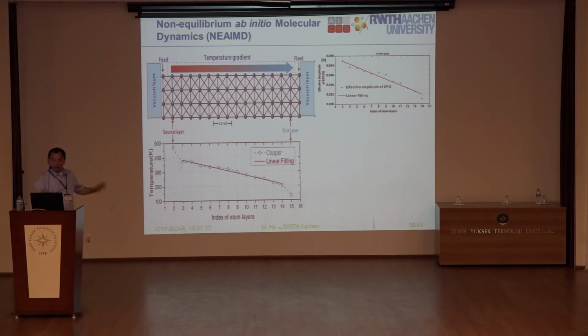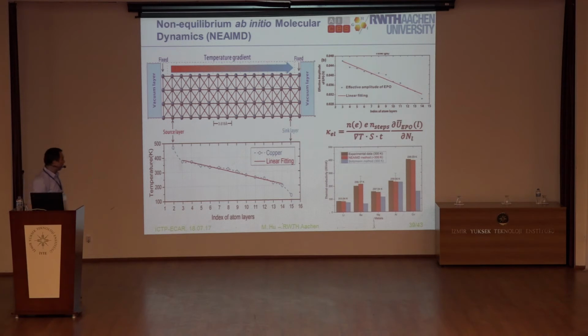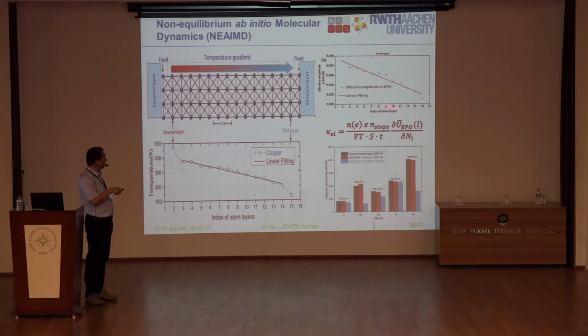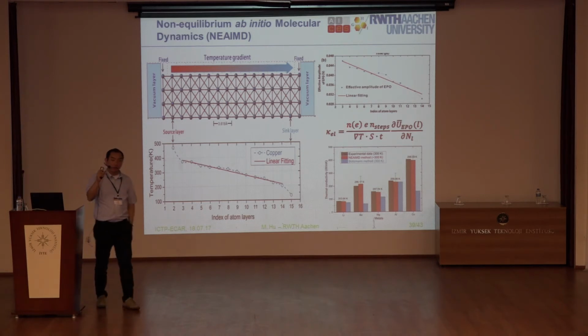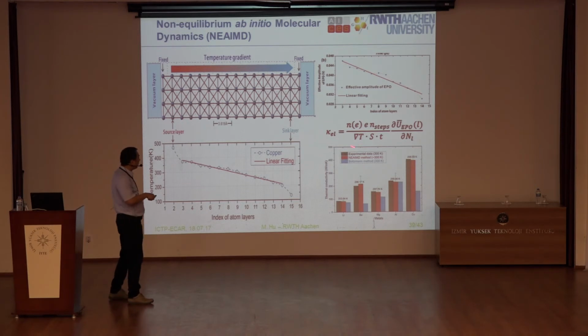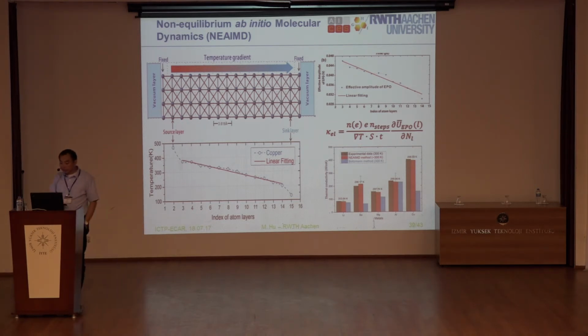So then with that, after some mathematical or physical reduction, finally we can correlate the electronic thermal conductivity with this gradient, the EPO gradient, partial U, partial N, and also the electron charge, and then this is the number of electrons in this EPO vibration. And then this is the temperature gradient of the lattice. And then the electronic thermal conductivity of some typical metals is compared with experiments. You can see that this is lithium, Be, magnesium, aluminum, and copper. You can see that our simulation method agrees with experimental values very well. So it's within like a 5% error, which is acceptable.